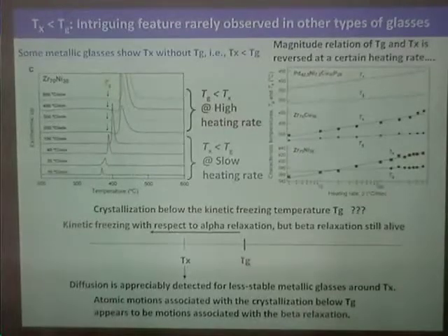Do you think that's related to the colloid experiments in Edinburgh, where they've seen colloidal crystallization out of a glass? Colloid, I don't know this colloid crystal. They also seem to find that if the glass is very dense, so the alpha relaxation died out a long time ago, very small displacements are actually sufficient to induce crystallization, and that's what seems to be allowing the glass to crystallize.